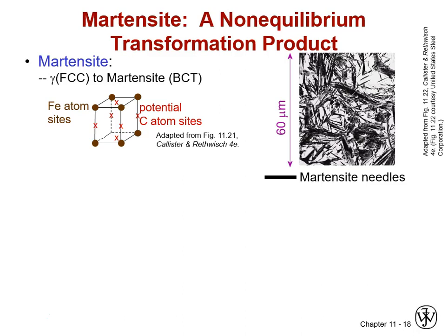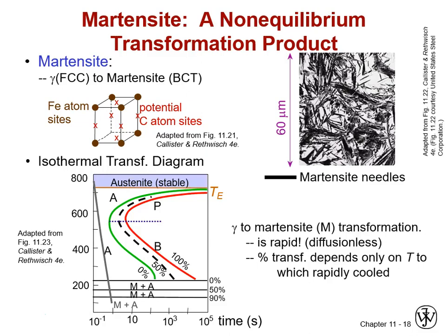Okay, speaking of martensite, if you remember back to allotropic transformations and the crystal structure of iron, your austenite, your higher temperature phase of iron, is face-centered cubic, and yet your room temperature crystal structure for iron is body-centered. And we touched on the differences in size of interstitial positions, especially those big octahedral holes that you have in the center of your face-centered cubic crystals, and how those are great for holding large amounts of small solutes like carbon. Well, that's one of the reasons why the solubility range that you see on the iron carbide phase diagram for austenite is so broad.